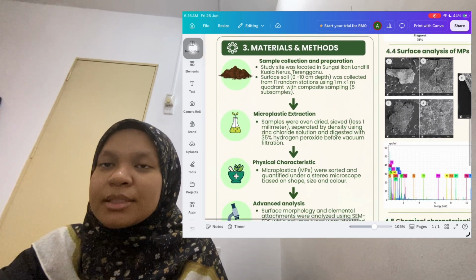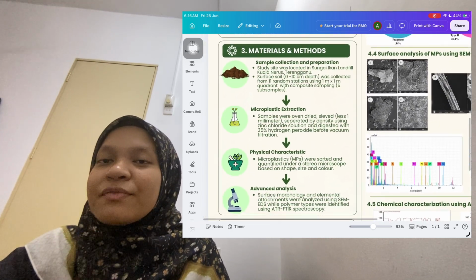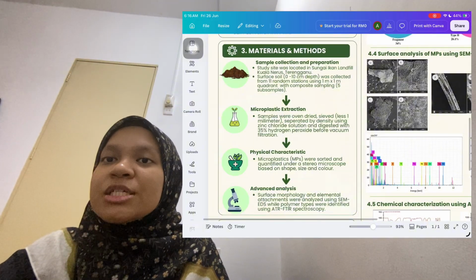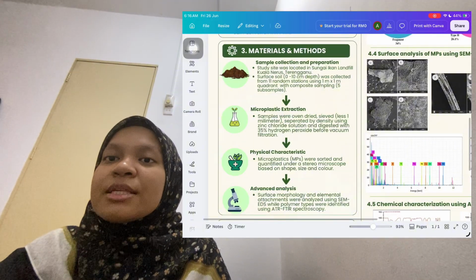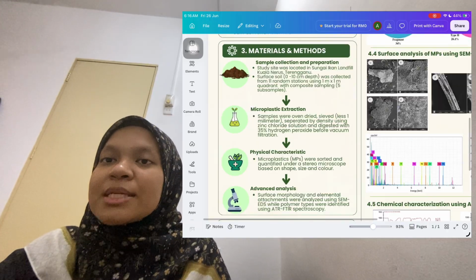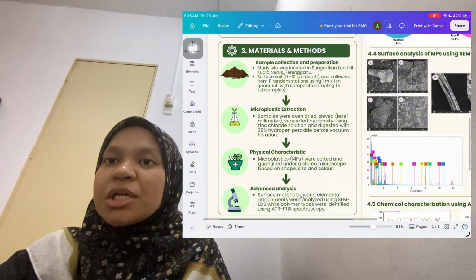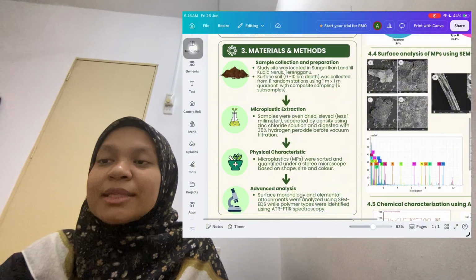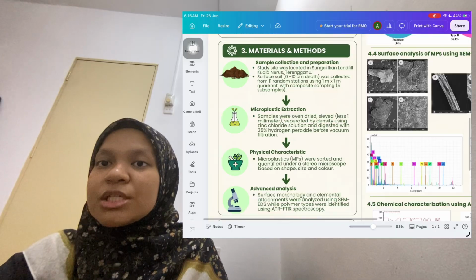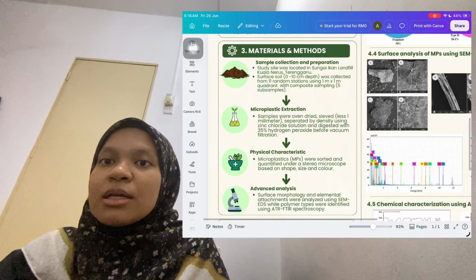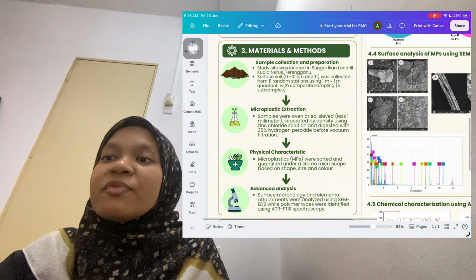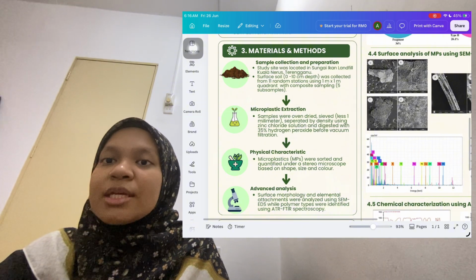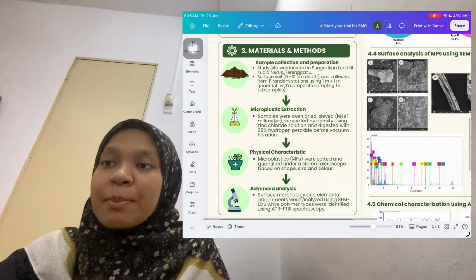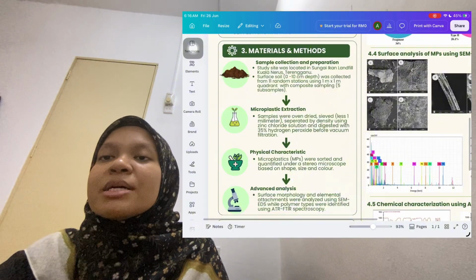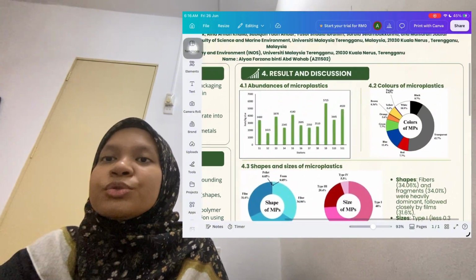For the materials and methods, 11 surface soil composite samples were collected from random stations across the active Sungai Ikan landfill in Kuala Nerus, Terengganu. The microplastics were extracted using density separation with zinc chloride solution, followed by 35% hydrogen peroxide digestion to remove organic matter, and finally isolated via vacuum filtration. They were then analyzed using stereo microscopy for physical sorting, SEM-EDS for surface mapping, and ATR-FTIR for polymer identification. Moving on to the key findings.